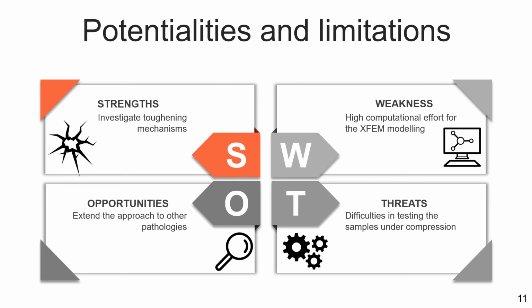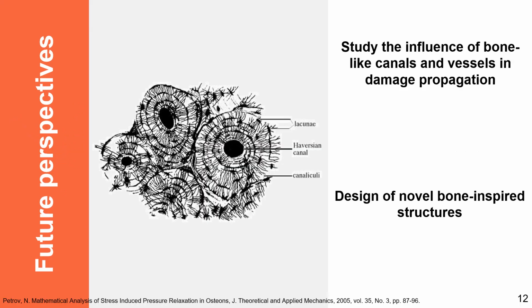The main limitations of the experimental study reside in the difficulty to reproduce lacunae as empty cavities due to remaining unfused titanium powders inside lacunae. Additionally, high computational effort is needed to perform extended finite element analysis. Despite these drawbacks, the chosen approach presents several potentialities by allowing to investigate toughening mechanisms and to extend the results to other pathologies.